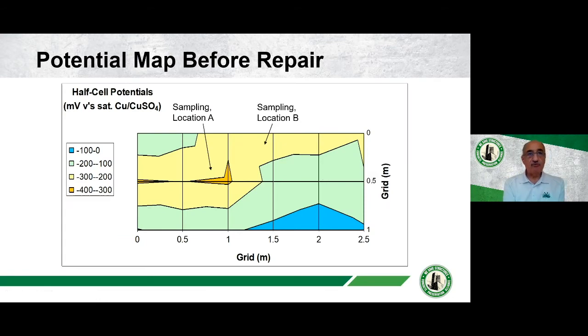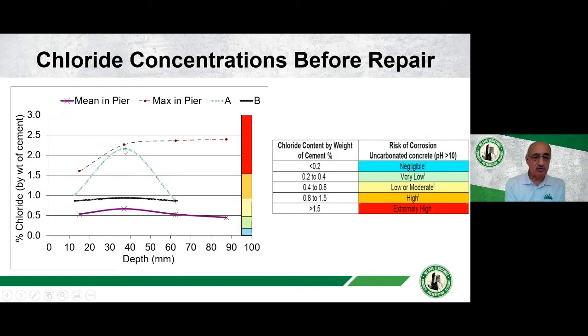Looking at the potential map of the structure beforehand, the area that we repaired, we could see that there was a high corrosion area, and it coincided with a high chloride concentration. As you can see here, we got as much as 2% chloride in the corroding areas, but even in other parts of the same structure, we'll be getting chlorides which were more than 1%. So 2% is considered to be extremely high. It's greater than 1.5%, and therefore it obviously needed to be replaced.